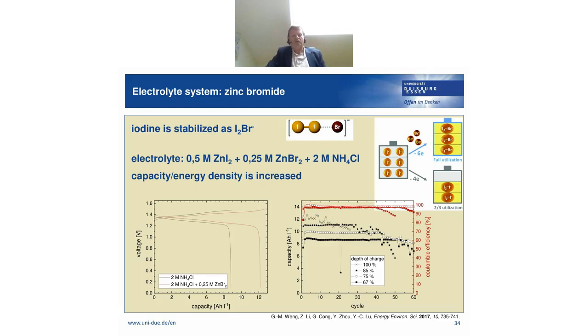So this has been reported in the literature, and the depth of discharge is of course important with respect to how many cycles can be obtained. This is depicted here in the right curve. We have the capacity again on the left y-axis in amp hours per liter, and again we have here the cycles and the coulombic efficiency. So when we try to charge and discharge 100% our battery, then we can only perform a few cycles. But once we go down a little bit with the depth of discharge, maybe to 75%, we can obtain again around 50 cycles, which is of course not enough yet for a good battery.